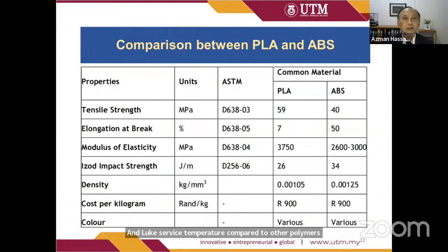So we can see here a comparison between PLA and acrylonitrile butadiene styrene. We can see that the tensile strength is much better for PLA. The modulus of elasticity or the flexural modulus is very good, but it is inferior, especially in elongation at break and impact strength. That's why PLA is considered to be relatively brittle.